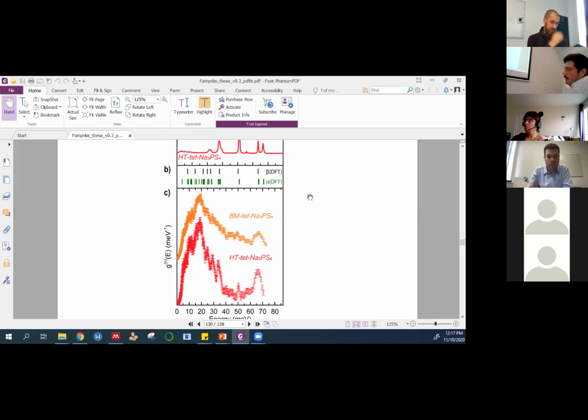First of all, this is the tetragonal sample, right? So between these two, there's not much macro strain, but there is significant difference in the micro strain. That is, from crystallite to crystallite, there are deviations in the lattice parameters. How would that change the phonon dispersion curves and your phonon density of states? I mean, all I have is a hand-wavy disorder argument, I think.